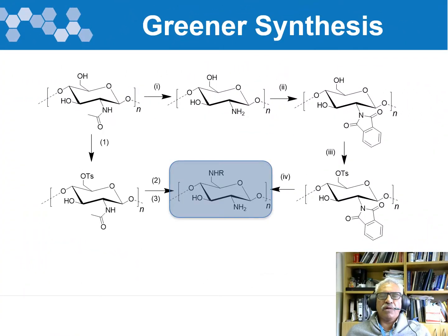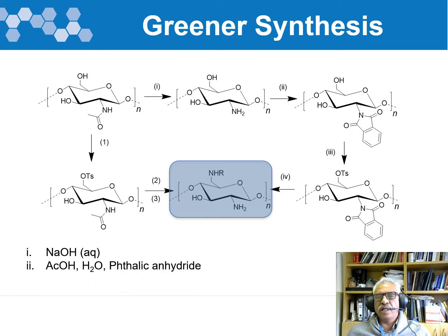So now, targeting this diamino chitosan, first, of course, we could use either the ionic liquid method of deacetylation or sodium hydroxide. Then protection using acetic acid and a water mixture with phthaloyl to put the phthaloyl group in there. Then tosylation of the 6-hydroxy in dimethylacetamide, which is a more environmentally friendly solvent. And then we could do a neat displacement with alkylamines directly from the tosyl to the substituted alkylamine. Ammonia itself doesn't work very well. You need high pressure sealed vessels, and we opted not to go that way.